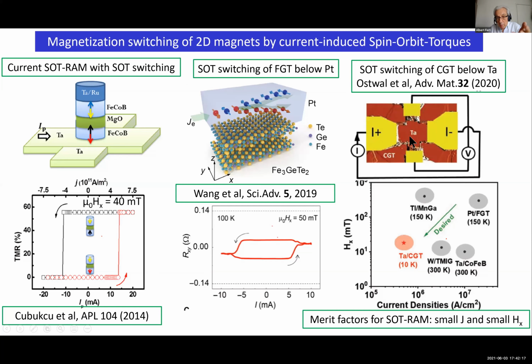So this is another interesting example. Again, the spin Hall material is tantalum, and the 2D magnet is another compound which is called CGT. And what is interesting is to compare and see if there is some advantage with the 2D materials, and this can be summarized in this diagram here. Of course, the merit factors are a small Hx, a small field to allow the switching, and also a small current density. So the desired direction is this direction, to have at the same time a small current density and a small field. And this diagram compares what is obtained with the 3D and 2D magnets.